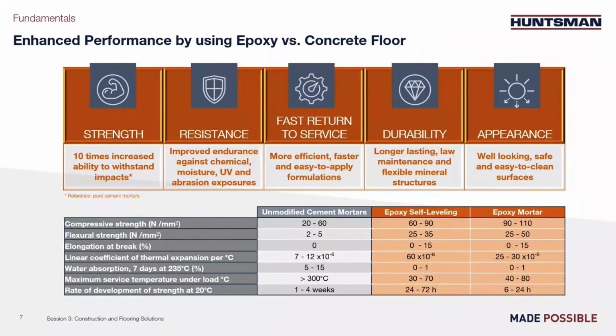The difference is visible when you look at the compressive strength, which is double in the case of epoxy mortar. This basically reflects the way you can place it on the floor. If the strength is improved, it is due to the high elongation at break of organic material versus mineral. Another advantage is the low water absorption of an epoxy and the faster cure of this thermoset material. Those advantages result in a better chemical resistance and a faster return to service.